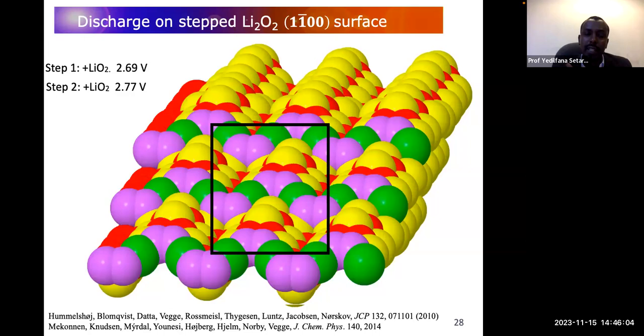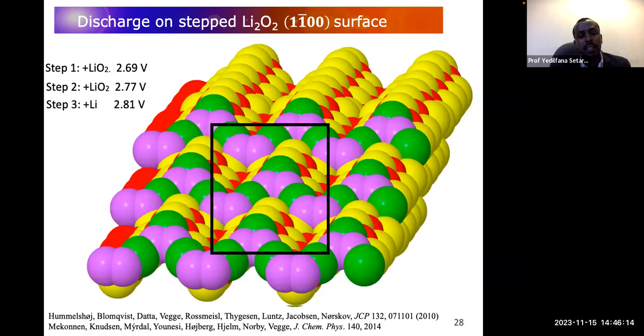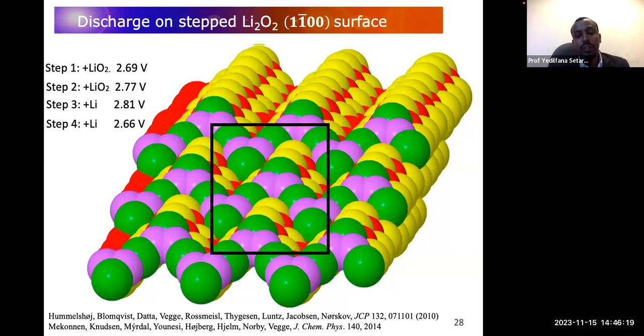And the second step in my model is again another addition of lithium superoxide with 2.77 energy. The third and the fourth are additions of lithium ion to the surface, then the growth mechanism will be finished with two formula units, Li2O2 formation. So this is my model. It's a four electron system model.